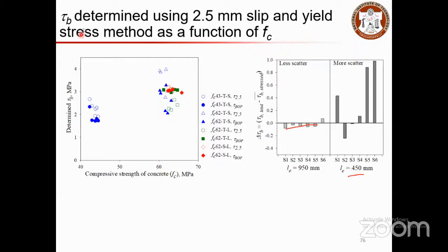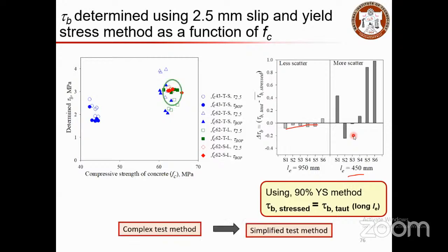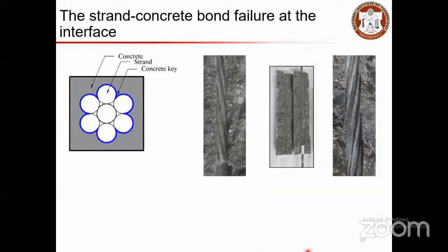If you look at the bond strength definition using the 2.5 mm slip and yield stress method, the two methods are giving almost similar results. When using the 2.5 mm slip method, the effect of the length or compressive strength cannot be ignored. Whereas if you consider the yield stress method, there is a bend-over point to consider the change in behavior, and then the effect of the length and pre-stress levels is minimized. In that case, the scatter is also lesser and the effect is achieved better. So from the complex test method, we could propose some simplified test methods using this 90% yield stress method, and from this we could understand some bond failure criteria at the interface as well.